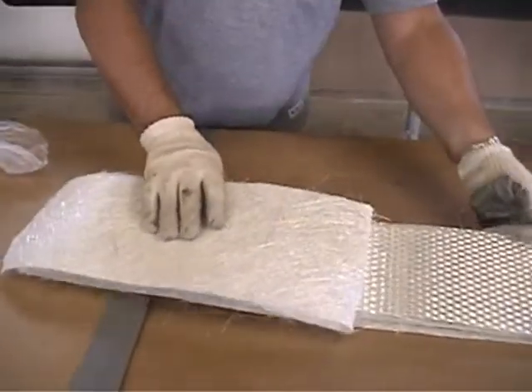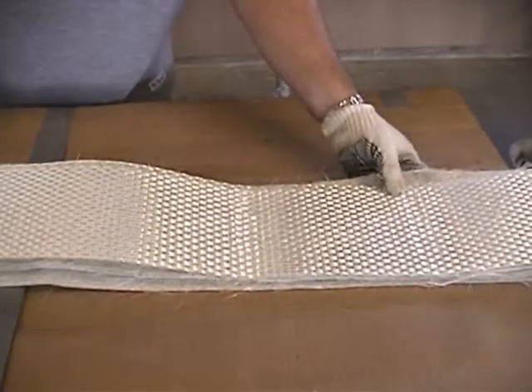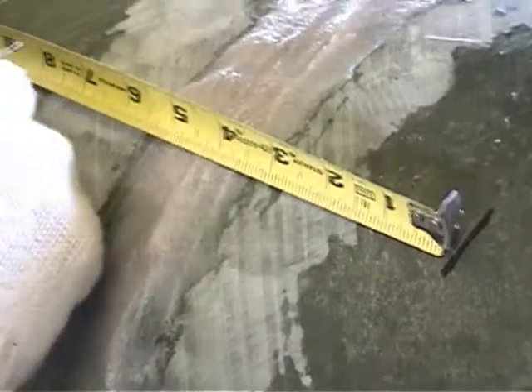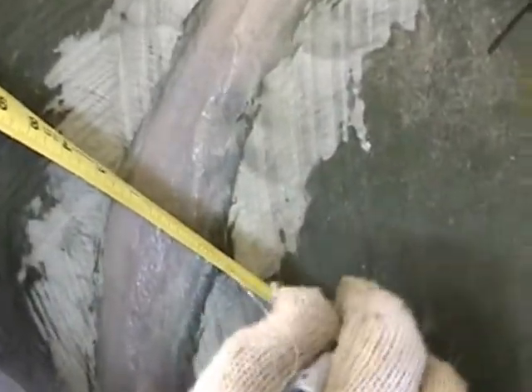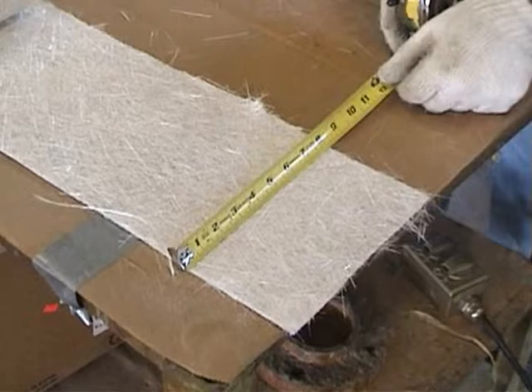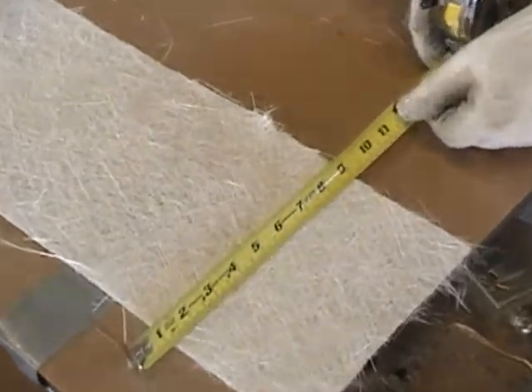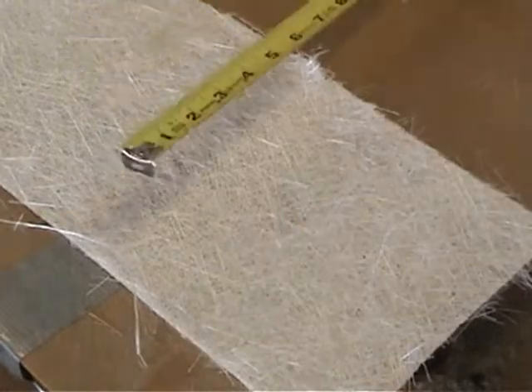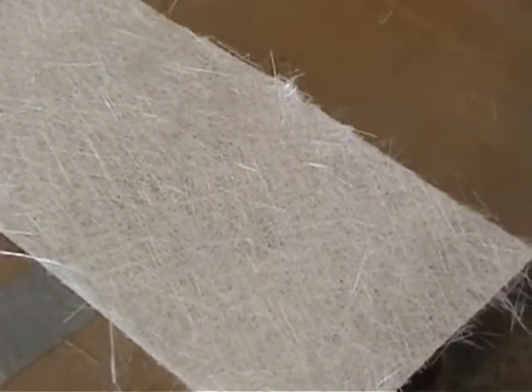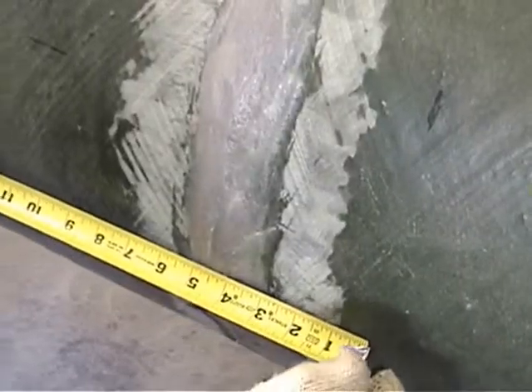While the resin is cooling, you can lay out the glass supplied with the kit and mark the pipe where you will sand or grind it. Always remember that you will have to sand or grind the pipe a 1/2 inch past the widest piece of glass you have. In this particular kit, this is our widest piece, which is our cover mat, so we measure it and add a 1/2 inch on each side, putting the halfway point approximately in the center of the seam.